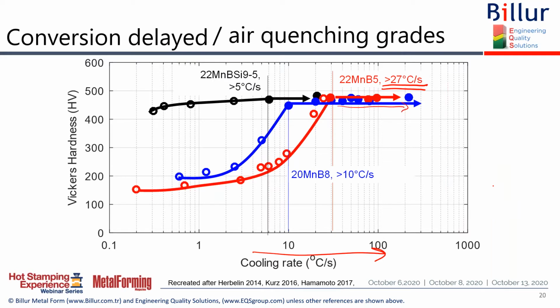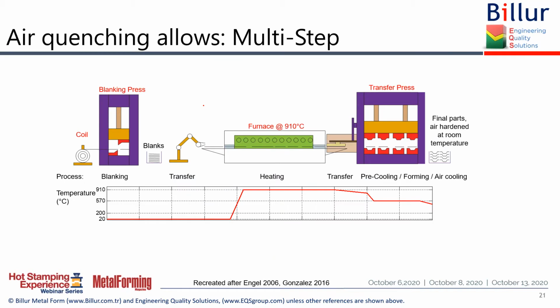And then we have this new air quenching grade. And as you can see, even at something like 1 Celsius per second, I'm still having almost 450 Vickers. And this allows us to use this grade in a transfer press. And in this case, I can do the forming and trimming. Even I can use cams to make pierces on the wall. And this is called a multi-step process.